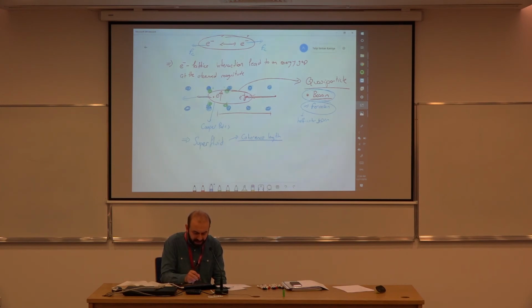And indeed, one way to destroy superconductivity in a material is to put in magnetic scatterers. For instance, if you start replacing niobium atoms with iron atoms in a niobium crystal, then these magnetic impurities will act as scattering centers. So before these Cooper pairs can form, the spins will start scattering from these magnetic impurities, and it will destroy the formation of Cooper pairs. So that's one way to look at it. It is related to the Kondo effect, but I wouldn't say it is the Kondo effect.